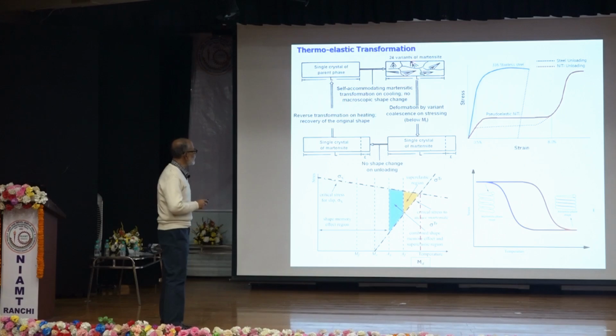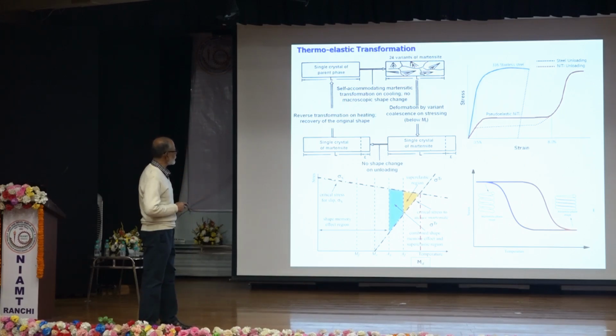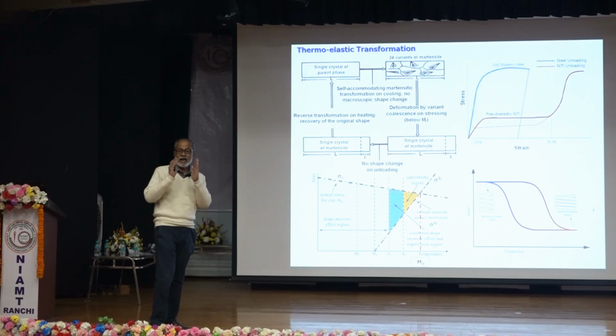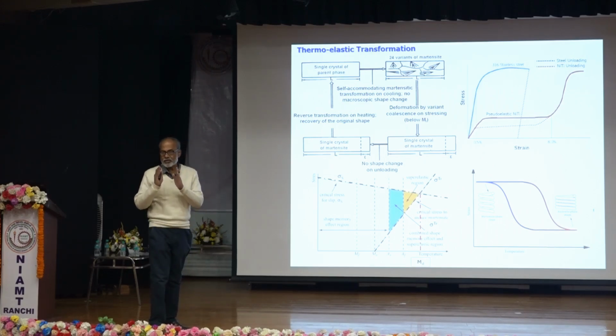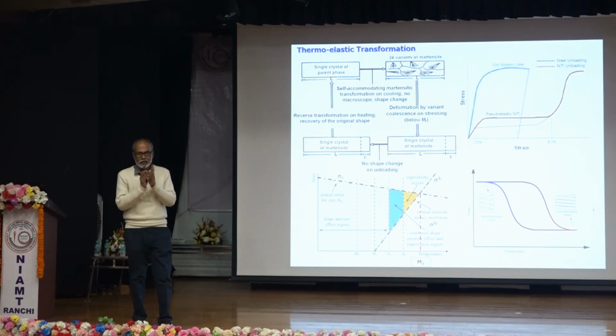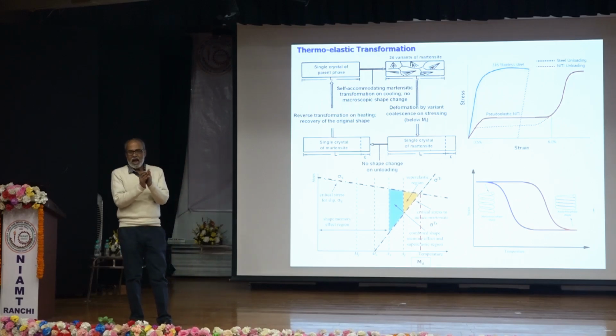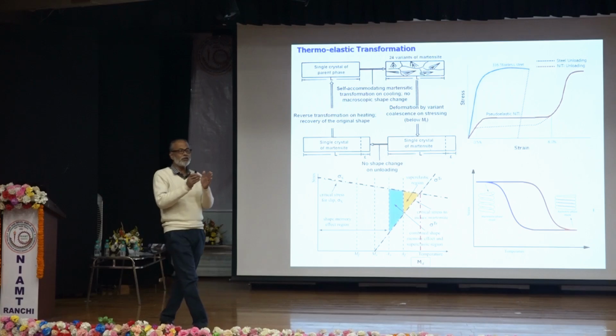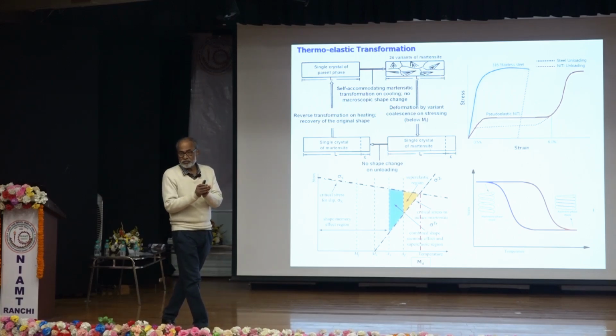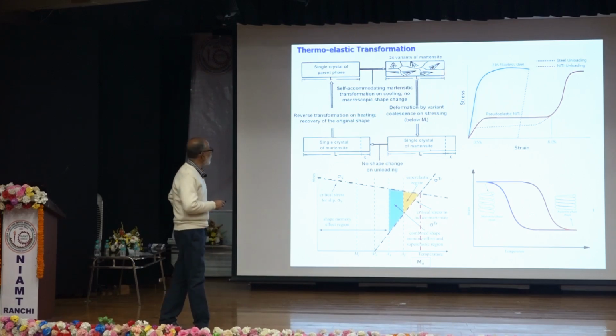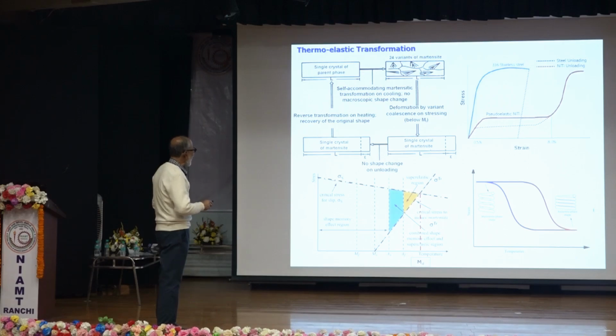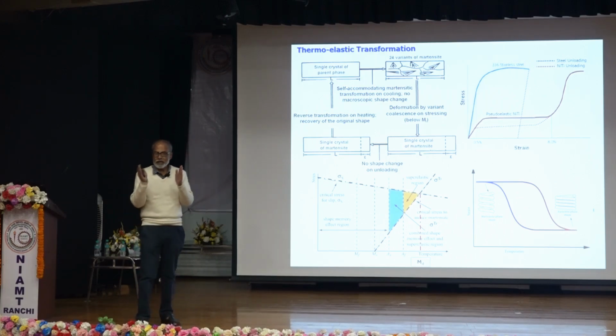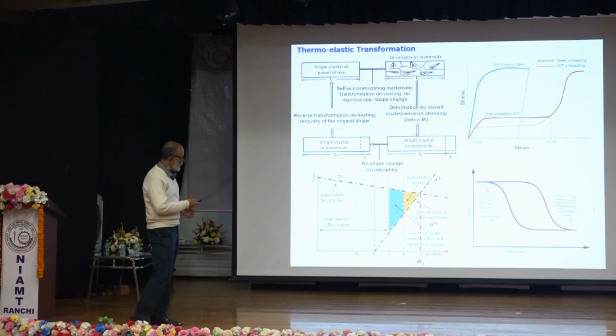Now the unique feature of twin martensite is that when you apply strain or stress on that, these variants will reorient. This variant will try to orient in the direction of minimum strain energy or favorable strain direction. All the variants will try to orient in the favorable strain direction. And as they are in same orientation, they will try to reduce energy further by combining with each other. There will be coalescence of these variants. First, they will orient in one direction and they will coalesce, right? And when they coalesce, they become a single crystal of martensite. If all the variants reorient and they coalesce with each other, what does it become? The product is single crystal martensite.